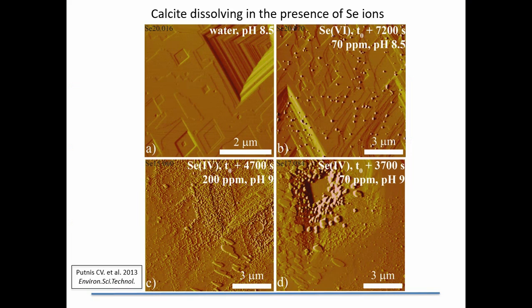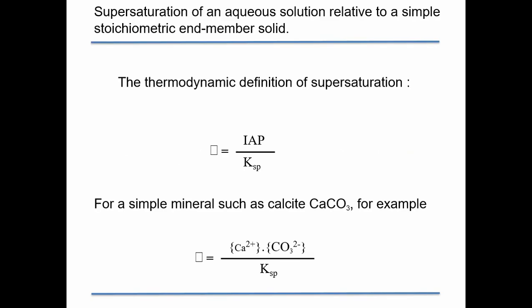Okay, what if we don't have a growth solution and we just add ppm amounts of selenium on the surface, which is what I did. So there we have dissolution of the calcite in A. If we have a look at the next images, we've got nanoparticles over the surface. Nanoparticles specifically in areas of very fast dissolution, not all over the surface. Eventually, they merge and cover the surface. But here, the bulk solution is undersaturated with respect to any possible precipitating phase.